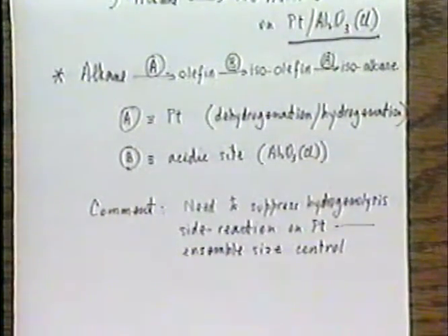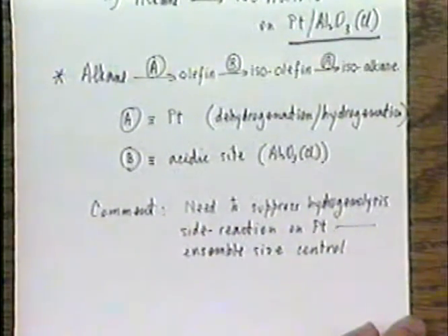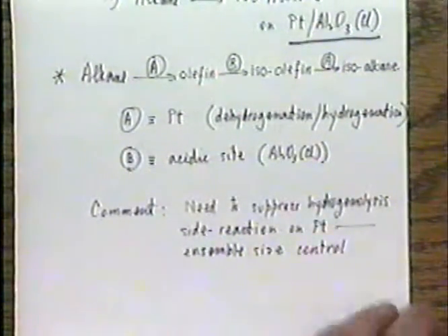And if you did decide that you wanted to suppress a parasitic hydrogenolysis process, you would refer back to the early lectures in this course where I dealt with the use of alloying with other elements to reduce the size of the surface ensembles that might be available for hydrogenolysis and hence suppress the hydrogenolysis process. Okay. I've got another one here which is related to that.